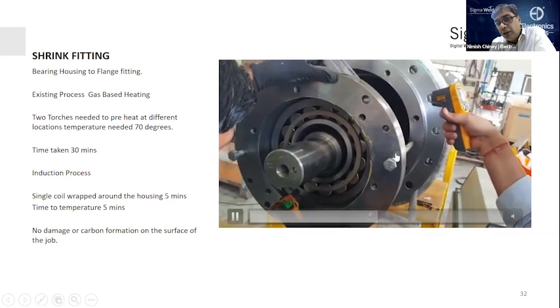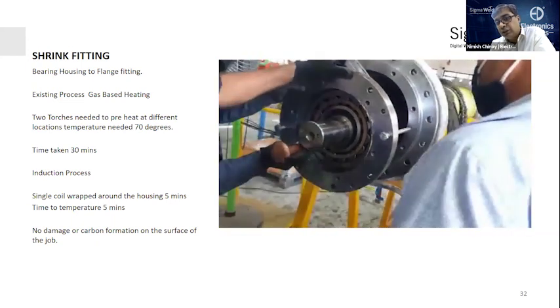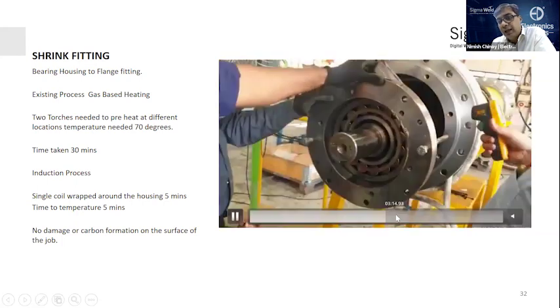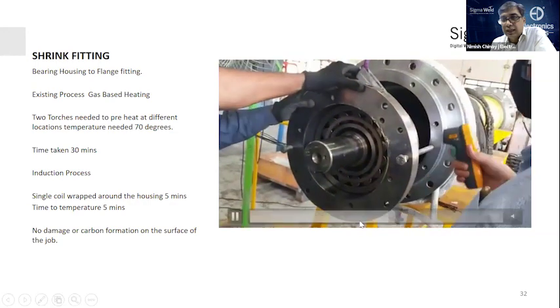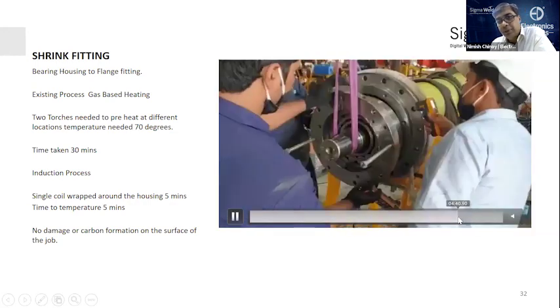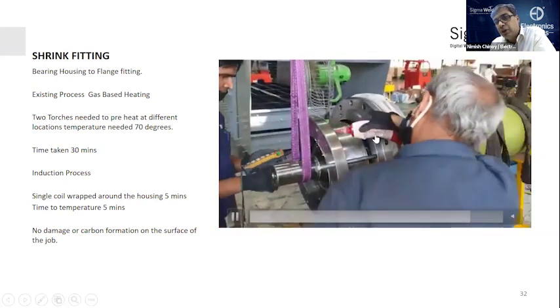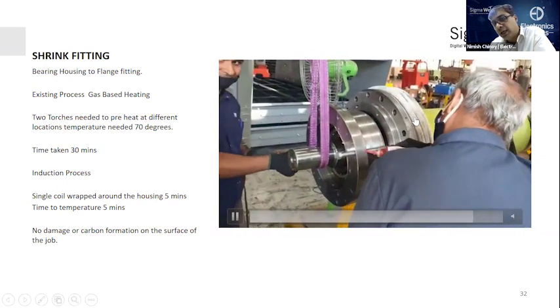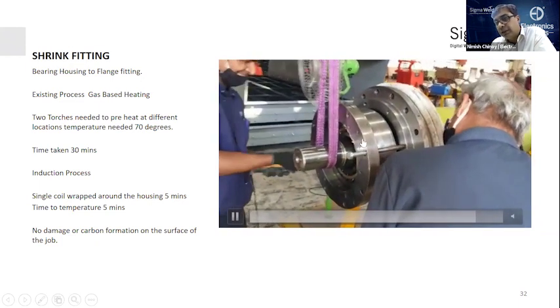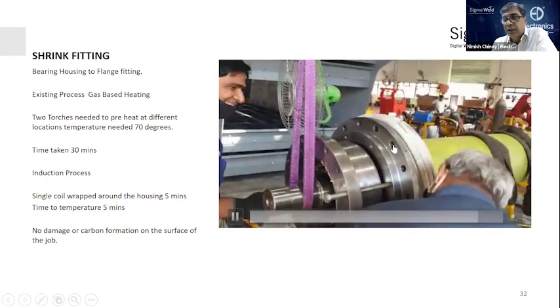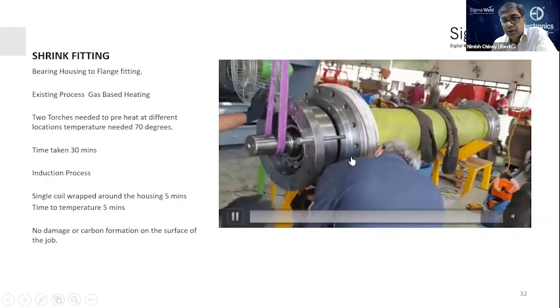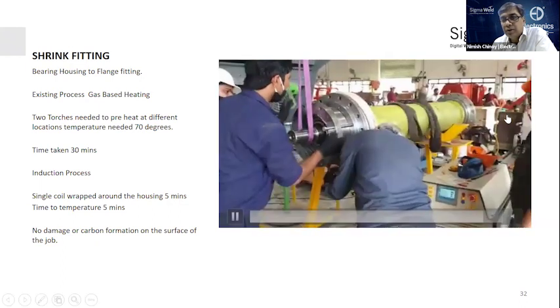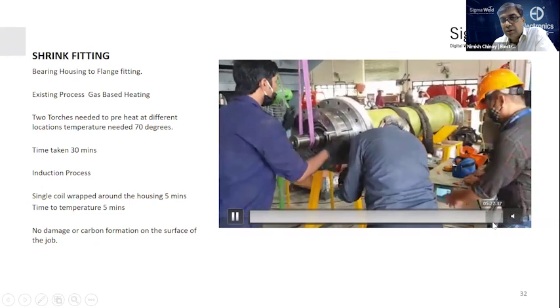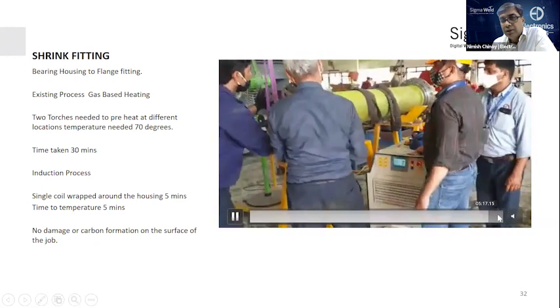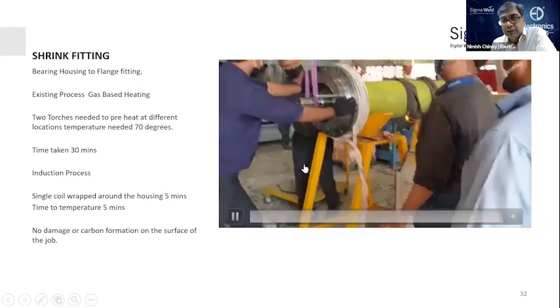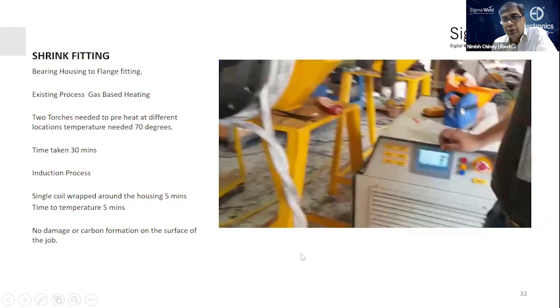When it does achieve it, the operator is in no rush to push this forward and carry out the shrink fitting job. There's a flange which is going to be mounted inside, and they'll simply slide it over to achieve the desired result. I'll just fast forward this so that people can get an idea as to what it does. So there you go. The condition is that the housing should get heated, but the shaft on the ID should not get any temperature. So this is where induction plays a major role, because it's inducing temperature directly only into the metal. So this is the shrink fitting process where they inserted a housing into the already pre-heated shaft.